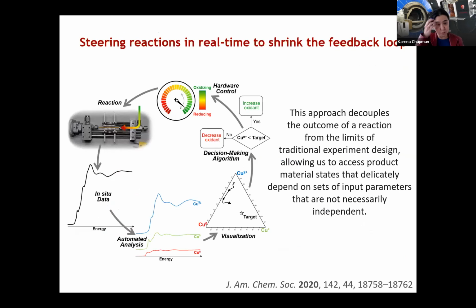There's obviously a long way to go in implementing these types of autonomous reactions. In terms of the chemistry, what this means is we can start to target particular oxidation states, which means certain oxygen vacancy concentrations, and it allows us to target states that we couldn't straightforwardly consider controlling with a single parameter. So instead of iteratively going backwards and forwards doing multiple reactions, we can start to think of just putting one set of reagents in and steering, once we know the right knobs, towards the right reaction.